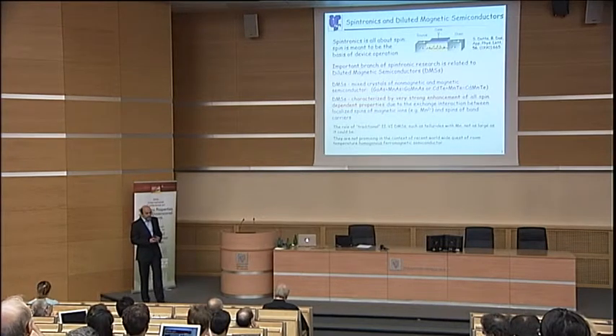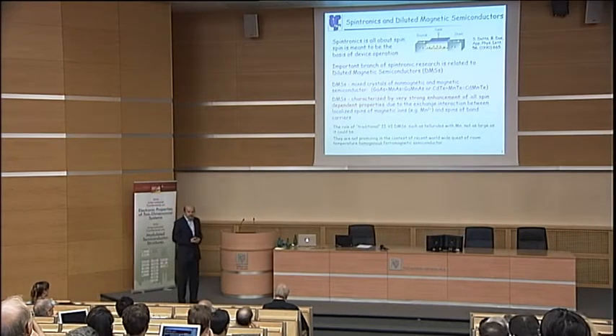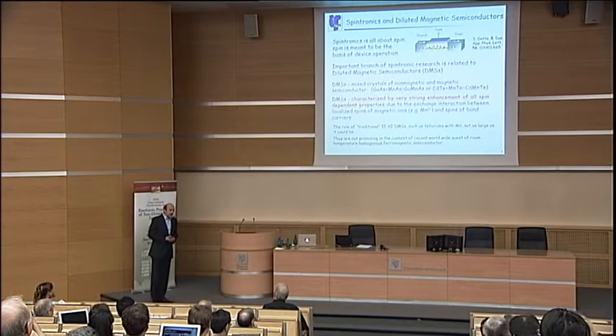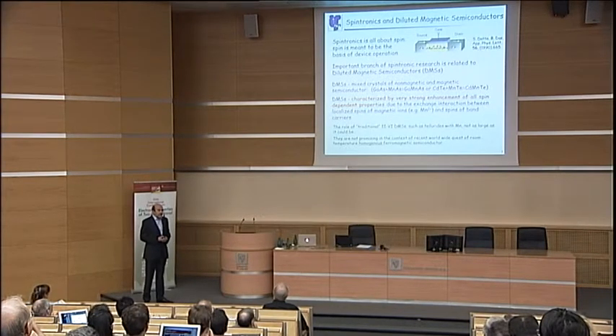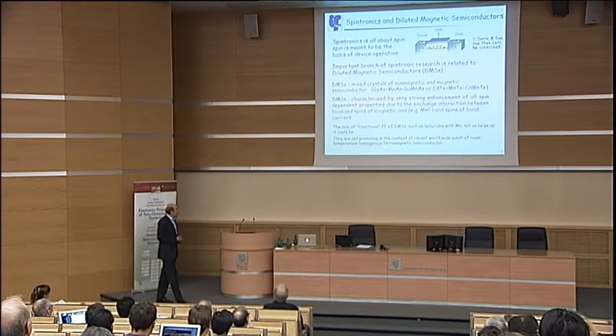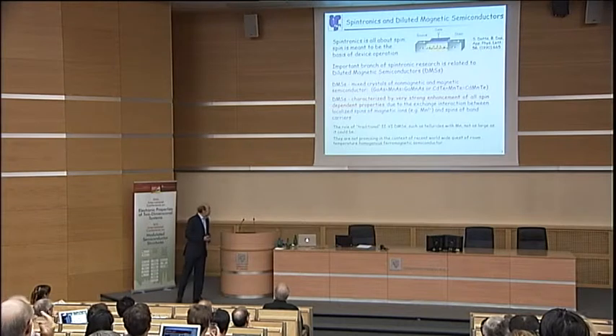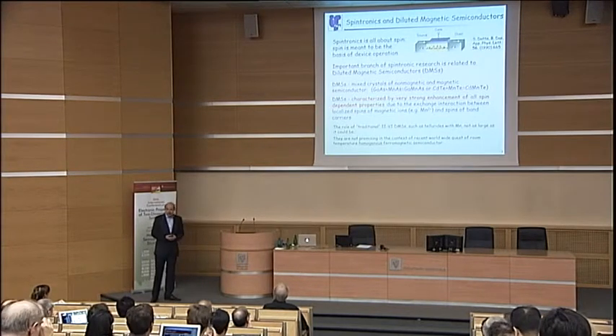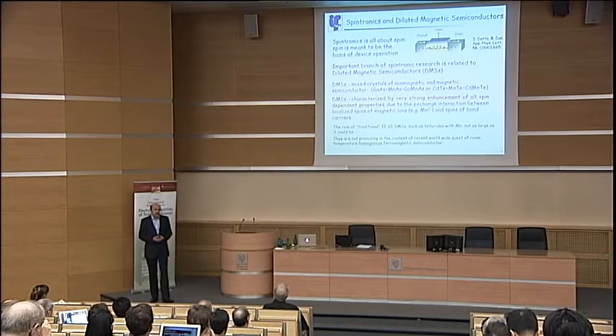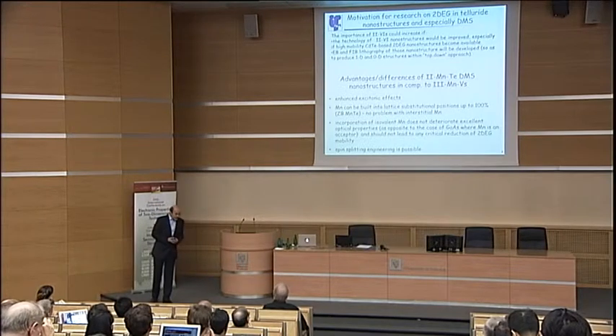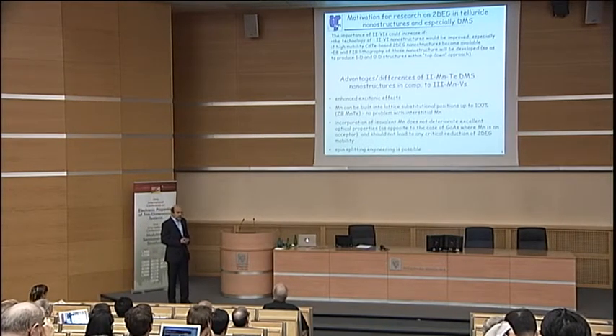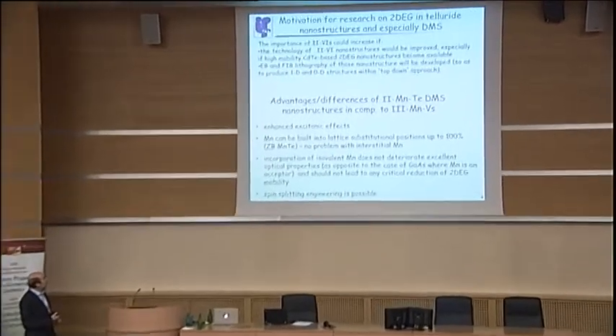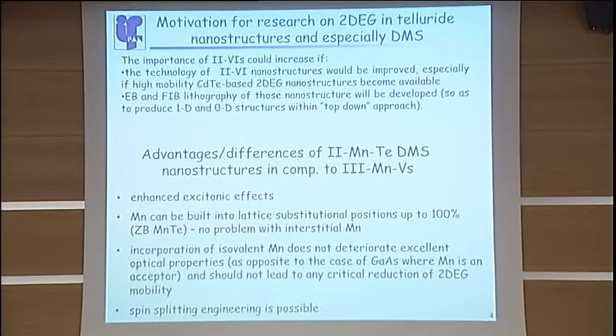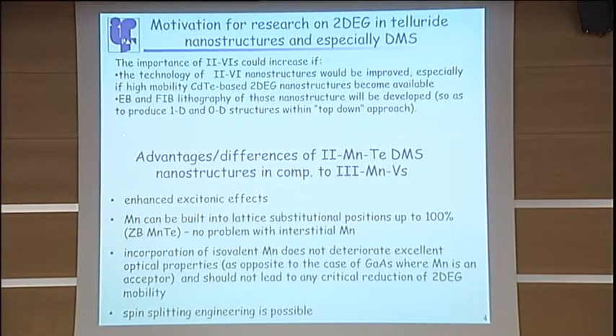And now, although II-VI diluted magnetic semiconductors have been the first diluted magnetic semiconductors, their role recently is not that large as it could be, in my opinion. And one of the reasons for this is probably that they are not promising in the recent worldwide quest of room temperature ferromagnetic homogeneous semiconductor. But I believe that their role can be increased if only the technology of those structures would be improved, and especially if cadmium telluride-based two-dimensional nanostructures would be available, and even more so if electron beam lithography and focused ion beam lithography would be developed.